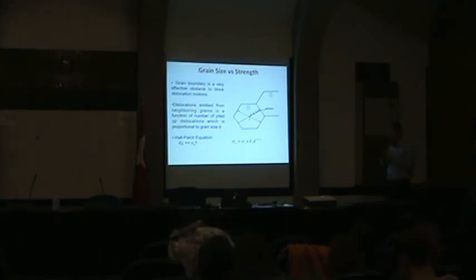So whenever the dislocation comes into a grain boundary, it stops. It thinks, how should I go? Changes the direction, keeps on going. But there's a delay in between coming to a grain boundary and following up on top of the grain boundary. And the scientists have already found that there is a relation called the Hall-Petch equation. So if we decrease the size of the grains, meaning increasing the amount of grain boundaries, that would give you higher strength in materials.